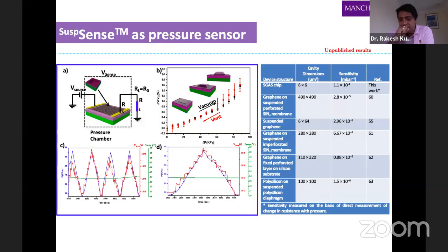Besides gas sensing, I was also working on a graphene-based pressure sensor, because a pressure sensor's sensitivity is determined by the thickness of the membrane. And I don't think anything can be thinner than single atom thick graphene. So we studied the suspended graphene-based pressure sensor, and we found that they are the best pressure sensors, especially when your pressure is very, very low. This has a specific application in the medical field, where you need to detect low pressures, whether it's body pressures or some other applications.